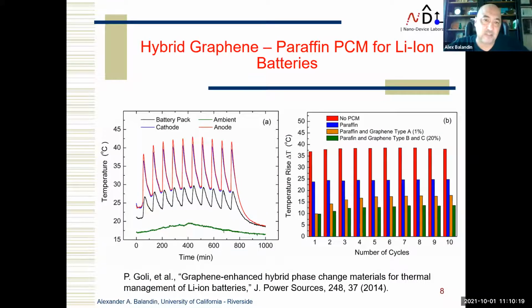Another advanced application of graphene is the thermal management of battery packs. Thermal management of battery packs is done differently than of computer chips. Typically, industry uses thermal phase change materials, PCMs. PCMs absorb heat rather than conduct it away. In our approach, we try to preserve the ability of PCM to absorb heat, but also increase its thermal conductivity by adding graphene flakes. And the results of cycling of battery packs with lithium-ion batteries show our material gives you an advantage compared to what's commercially available.